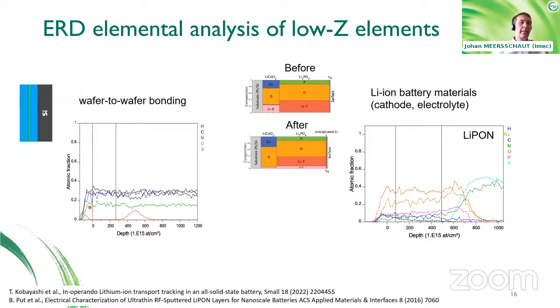And you see that you have the different elements like nitrogen, carbon, hydrogen, and so on, and that at the interface an oxide is formed. And this is a property that you probably also could probe with electron microscopy. The differentiating property that we can also probe here is the characteristics of the hydrogen depth profile.